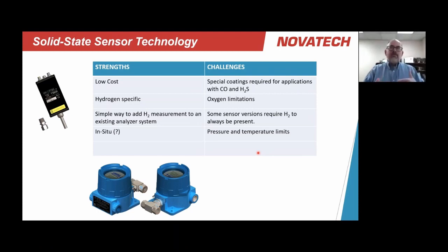In terms of challenges, we do have to be cognizant of the limits when it comes to some of the contaminants that can cause issues with the sensor. Similarly with oxygen as well. If oxygen is present, we do have to be careful in the selection of which sensor we're using. There are also sensors which are designed or work best when hydrogen is always present. And if we take the hydrogen away, the sensor may need some time to come back up into operating function. And because, as I described earlier, as we increase the number of hydrogen molecules in front of the sensor, this is basically a partial pressure device. If I increase the pressure of the gas in front of the sensor, it's essentially the same as cramming more molecules into that matrix, and therefore I can get a change in the reading. So there are pressure and temperature limits to the sensor, but also there are pressure and temperature compensation requirements. I have to be able to compensate for those changes in pressure and temperature in order to get a correct reading.